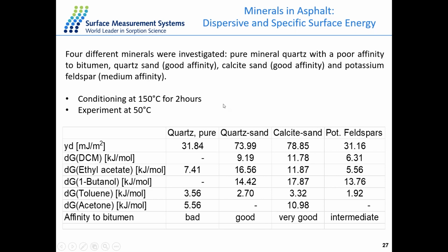What we've done is carry out our experiment with a preconditioning at 150 degrees for 2 hours, and we run our experiment at 50 degrees. Here we have a table of our dispersive surface energy results. We've also injected a few other molecules to understand the interaction between our materials and these polar molecules. So we have dichloromethane, ethyl acetate, butanol, toluene, and acetone.